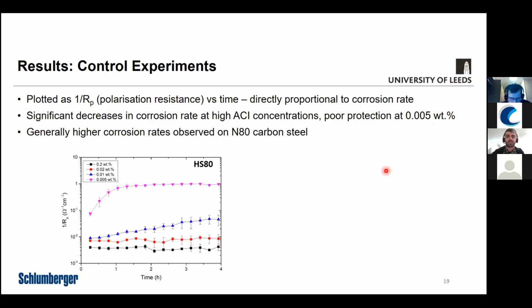So these are some of the results that we've got. And what these results are showing is essentially our polarization resistance over the 4-hour experimental period. So what we've done here is plot the results as 1 over RP, polarization resistance from the LPR measurements, rather than plotting the corrosion rates. So the reason for doing this is that it can be tricky to calculate a corrosion rate from an LPR measurement at times. It's not always scientifically accurate.